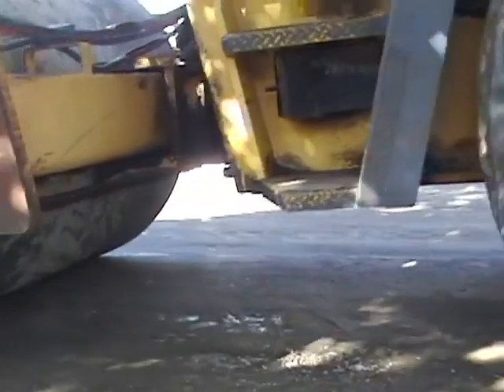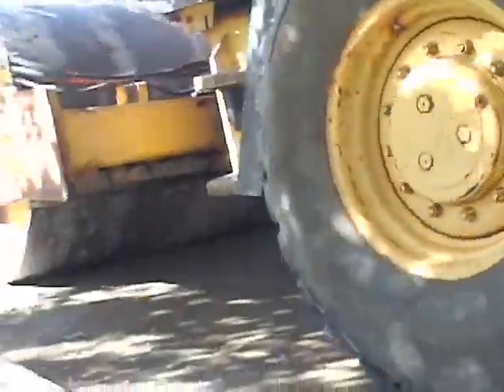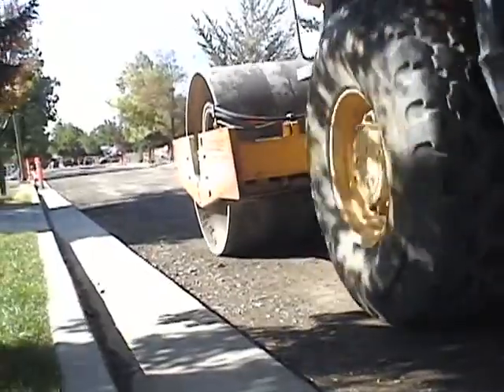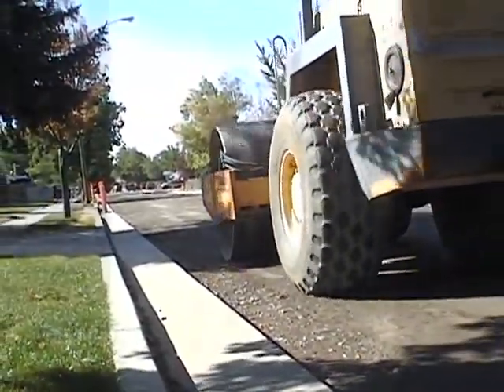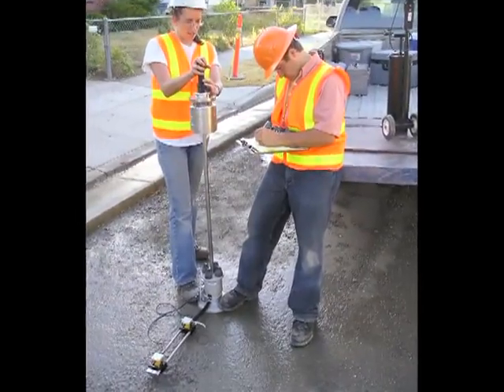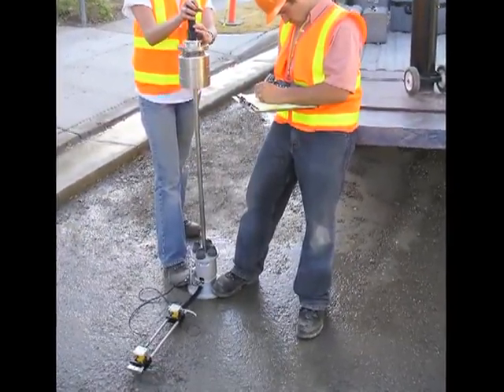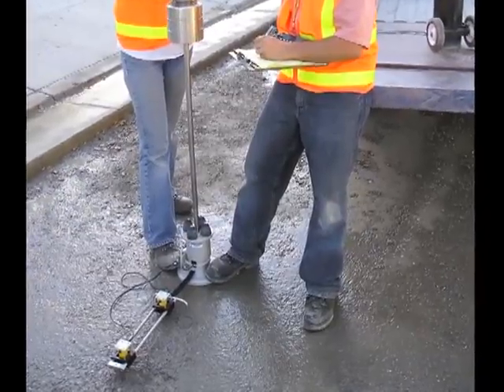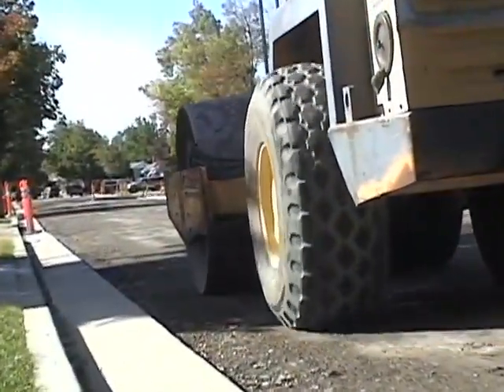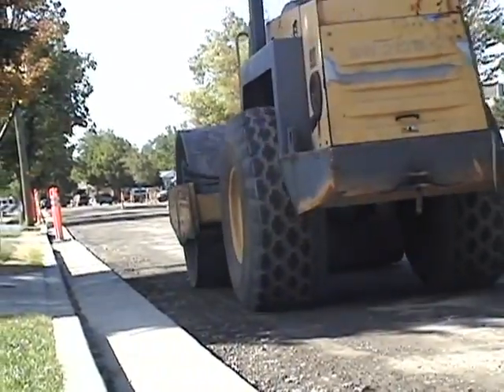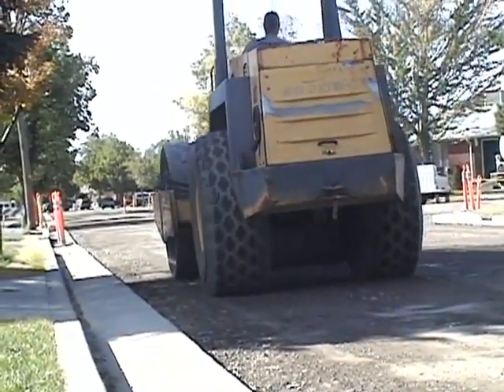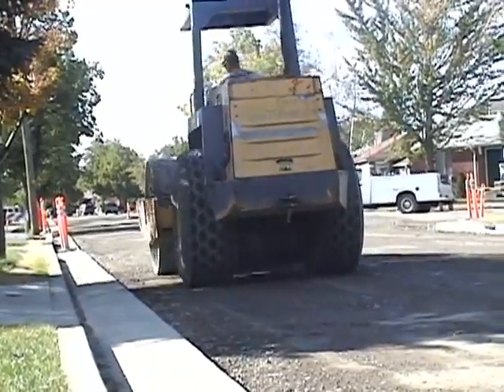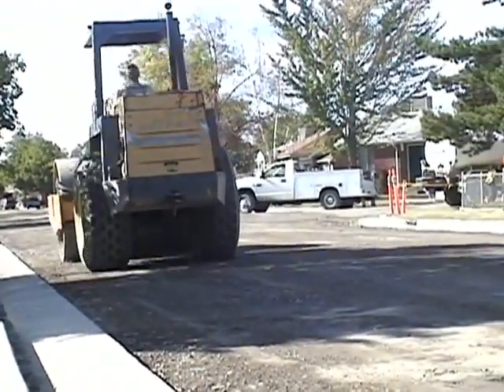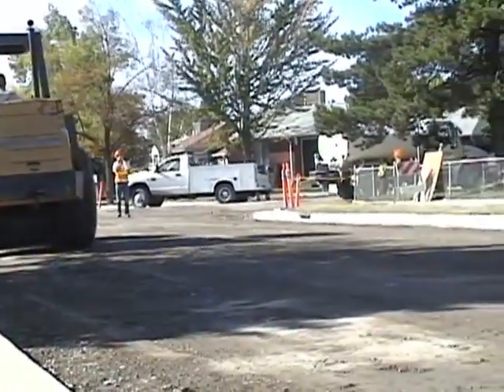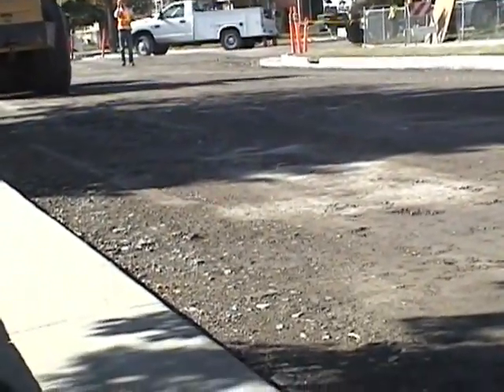48 hours after final compaction of the CTB was sufficient time for the CTB to gain significant strength, especially during the hot summer month of August experienced in 2008. The target reduction in strength of the CTB was 40%, using the portable falling weight deflectometer. Between 2 and 4 vibratory roller passes were required to achieve the target reduction in CTB strength. Measurements were made between each individual pass. For clarification, 1 pass is down, as opposed to down and back. Once the target reduction was reached, the contractor was notified to discontinue vibratory rolling.